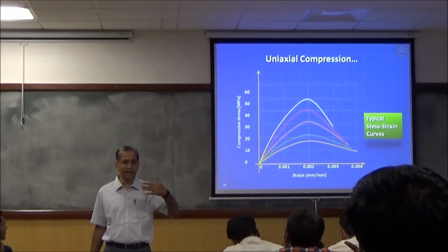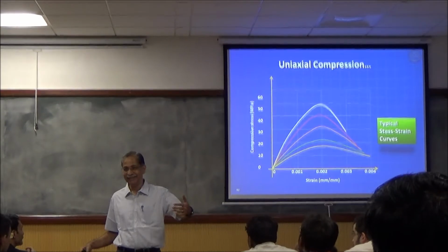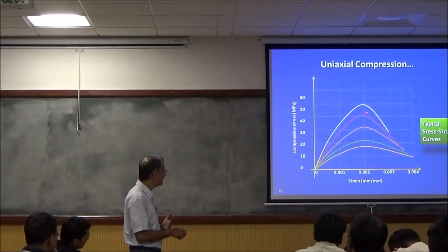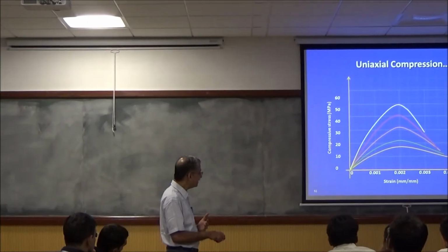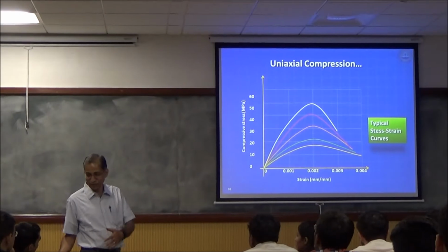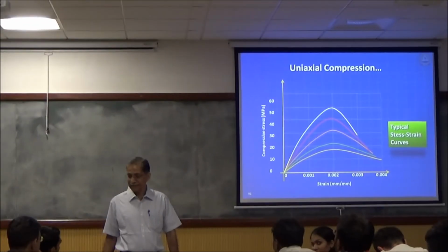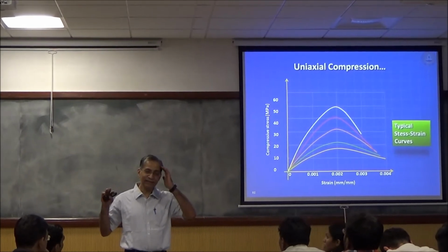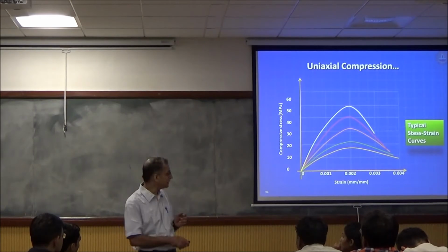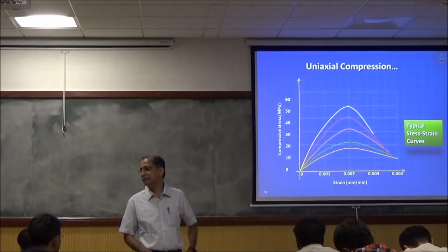As the grade of concrete increases, the failure strain decreases. So can you put it another way? As the grade of concrete increases, the material tends to become more brittle, because the larger the failure strain, the greater the sign of ductility.